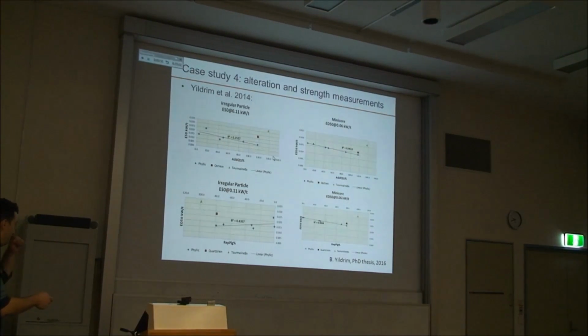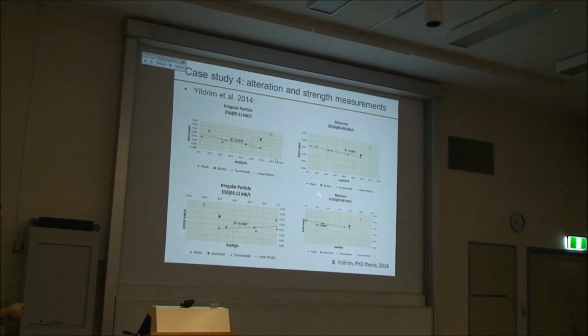On the right hand side, you can see the same ore or the same alteration profile, but by using the mini core. So the mini core are the cylinders. So now by using the cylinders, he's shown that there is a strong correlation between this process alteration index, or the alteration measures, which is the addition of quartz or replacement of plagioclase. And you can see the increase in the correlation factor was significant. So there is a significant softening of the ore with the actual alteration properties. And it can be quantified.